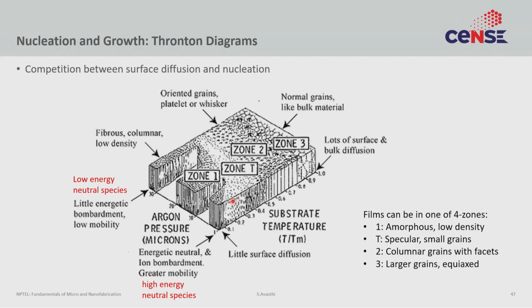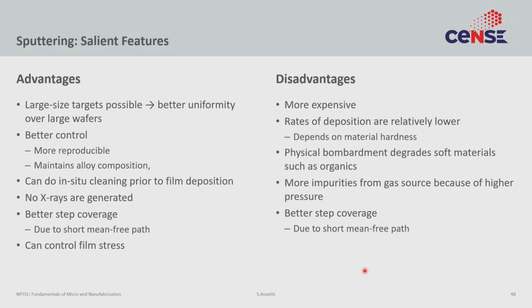And that higher energy means you don't need to get that energy from the substrate, you are now getting that energy from the electrical power. So all that happens is that the range of zone 1 reduces, becomes narrower, zone T comes to lower temperatures, zone 2 comes to lower temperatures, and zone 3 comes to lower temperatures. So this is how people play with the morphology of the deposited film given access to pressure and temperature. These conditions become significantly more complex when you are trying to do reactive sputtering, but that is something that we will not discuss in this course.